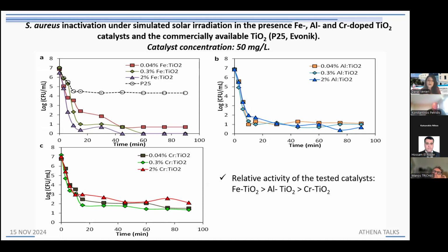leads to high levels of turbidity. So the transmittance of the light is prohibited. Anyway, you can see here that under the specific operating conditions and with the use of that concentration of catalyst under simulated solar light, we achieved quite successful, let's say, reduction of our bacterial concentration. We achieved 0 levels, as you can see in the diagram A on the left, but in many other cases, we saw